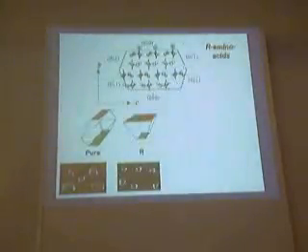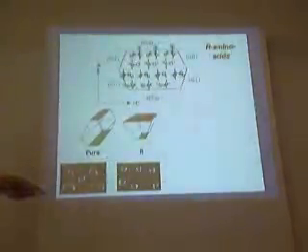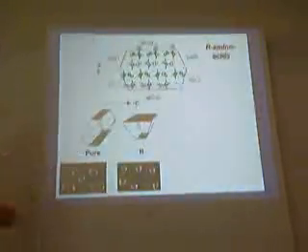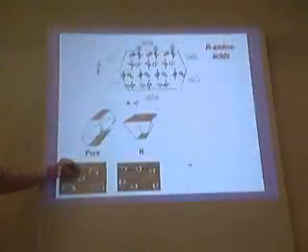Let's say another experiment. This is again the same crystal, and we can monitor this by the morphology. If you grow the crystal in pure water, you get a bipyramid. But if you grow it in the presence of R amino acids, you get a half pyramid, which means that this surface has reacted with the R amino acids, and this face is now very well expressed.